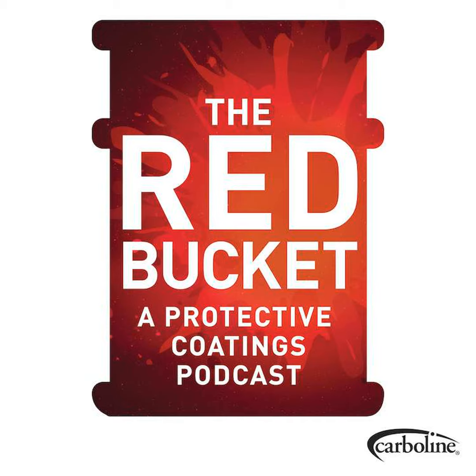right? It really is important to have something that withstands the effects of UV light, moisture, and rain for a really long time, because what'll end up happening is typically it's a process called photochemical degradation. And what'll happen with non-fluorinated top coats is you'll start to see some breakdown at the molecular level. You won't see it. That's the whole idea, right? The only thing that you will see is usually a loss in gloss over time.